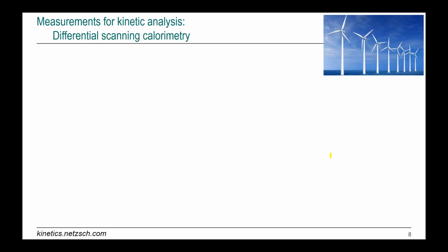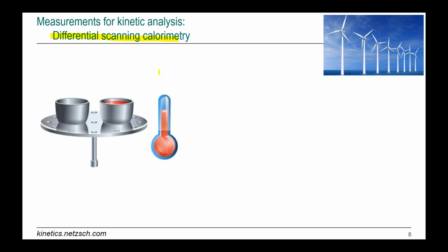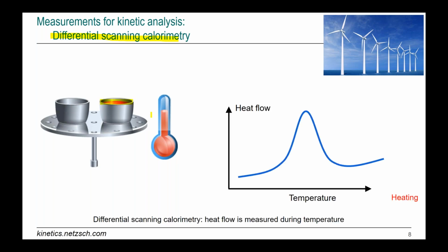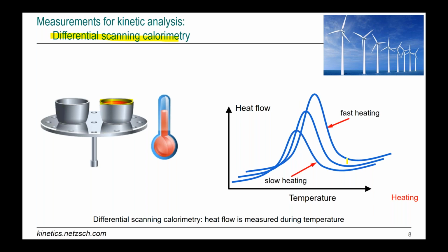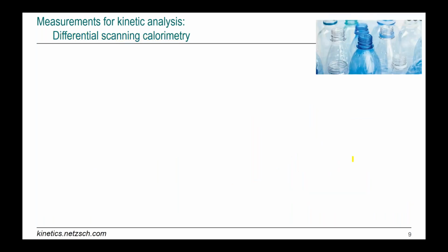Here we have curing. For curing, the mass is the same, but we know that during curing the reaction is exothermal and some heat production happens. So we can measure this heat energy released during the chemical reaction. For this, we use differential scanning calorimetry—an instrument with two crucibles. We put in a sample, heat it, and measure heat flow. If there's heat production, the DSC curve has a peak. During heating we can go fast or slow, giving different peaks. If heating is fast, the reaction is very intensive and the peak is higher. For slow heating, the reaction is less intensive, so the peak is not as high.